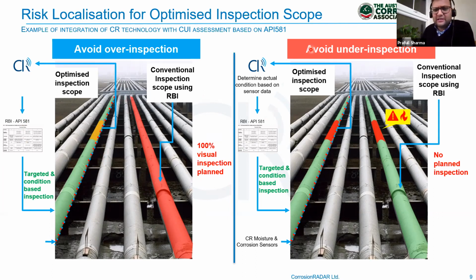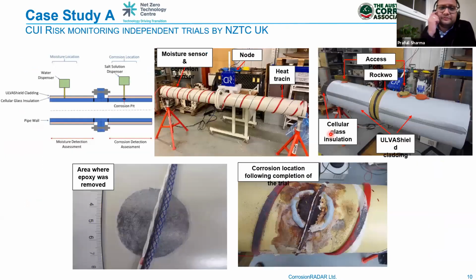Similarly, on the right-hand side is a scenario where we want to avoid under inspection. So in this case, again, the same pipe. If it is green all throughout using RBI, there won't be any planned inspection. However, in reality, the water might have gone in and nobody will notice that. So that will be captured by the sensors. And then it will recommend that, yes, it is indeed right that it's green, but no, there's a red condition developed locally, so go and inspect it at some inspection interval. So this needs to be inspected for safety reasons. So this is the next step of combining with RBI. How can we take condition-based data to effectively define the inspection scope? There are a few case studies I'll go through.